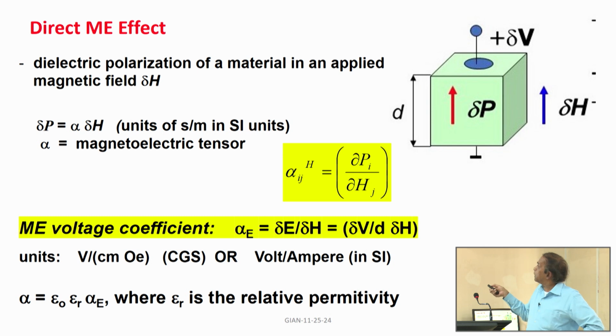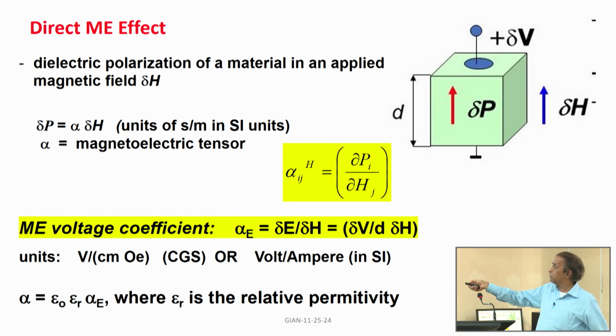Now, if I apply AC magnetic field, there is a change in polarization, and these two quantities are related through this expression, and alpha is the magnetoelectric tensor. And so, you define alpha with the superscript h, that means you are applying a magnetic field, and that is equal to the change in polarization to the applied magnetic field.